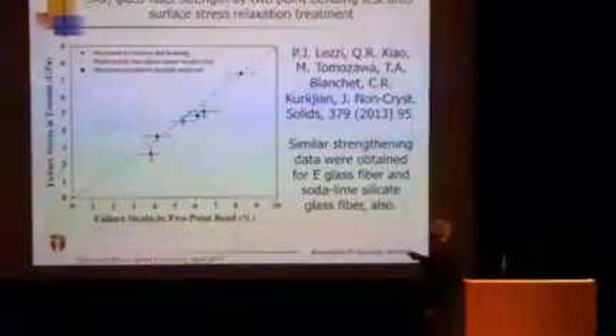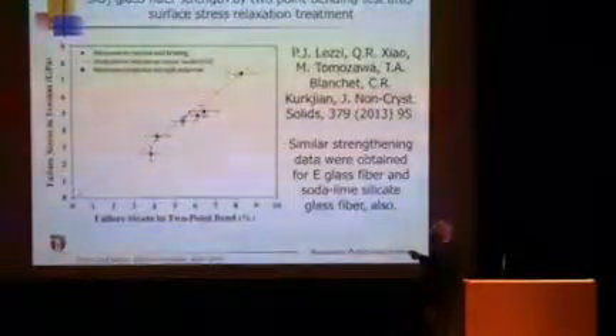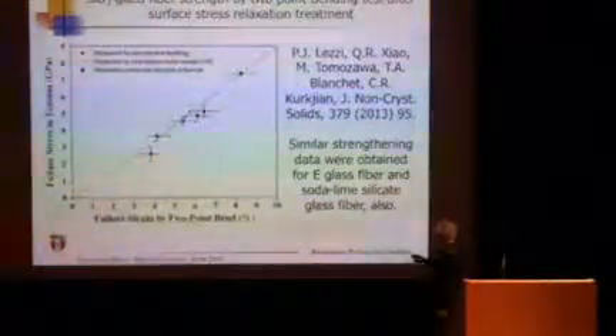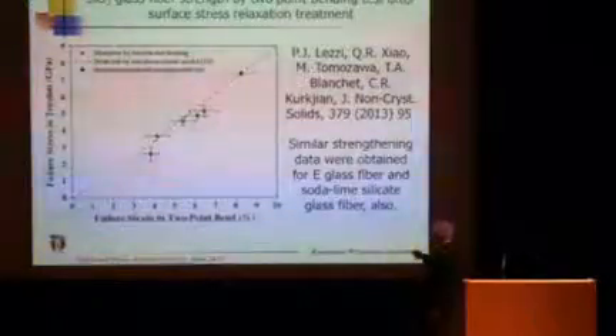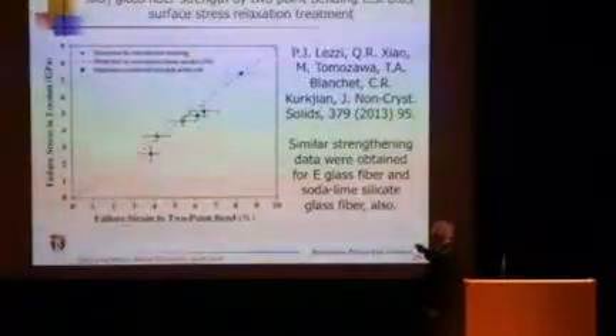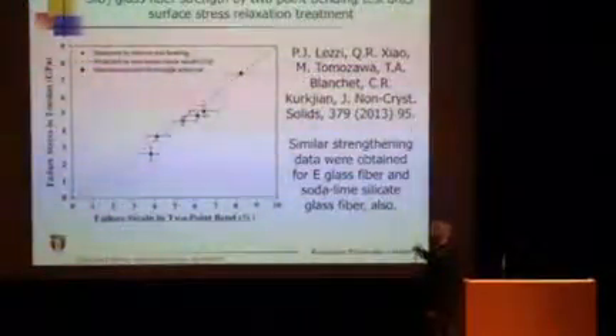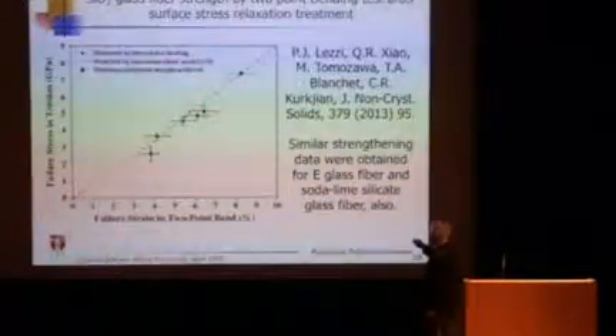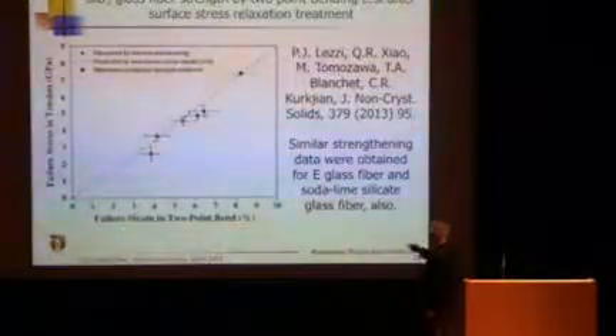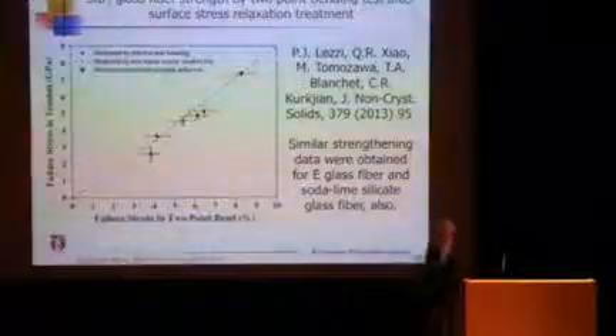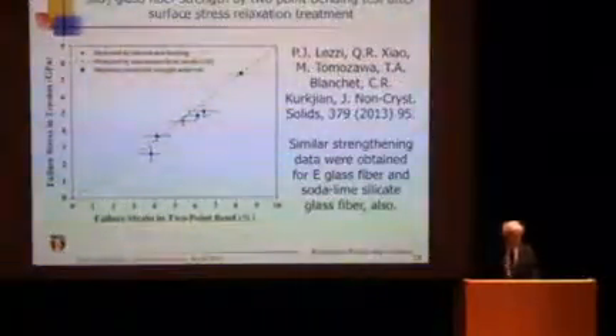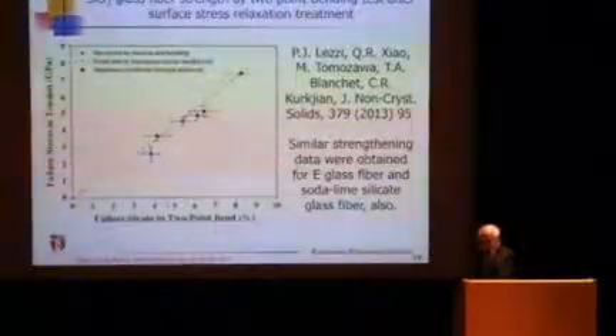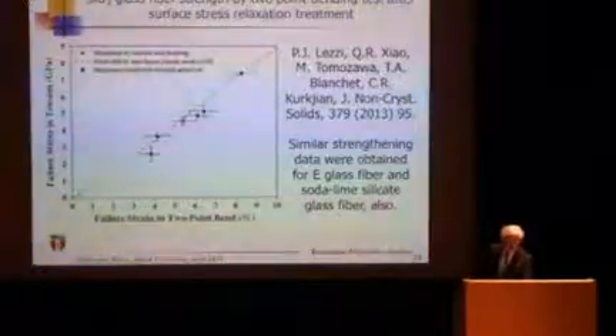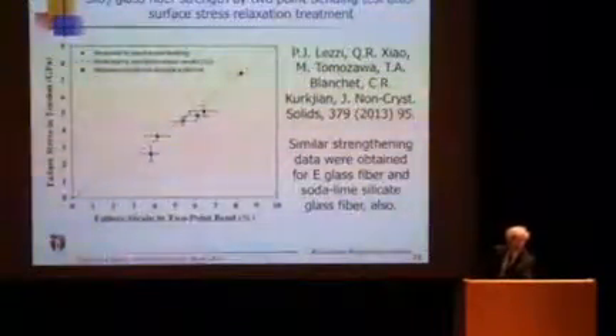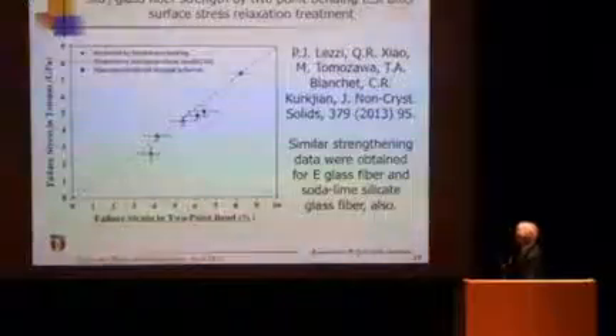This is the normal strength of silica glass fiber, the room temperature optical fiber. When you heat it, normally it gets weaker. But when we treat it at 200 degrees, 1, 2, 3 gigapascal, then we got this much higher strength fiber. It's 30% higher by a simple process. It doesn't take much time in this process. So we definitely demonstrated that glass can be made stronger.